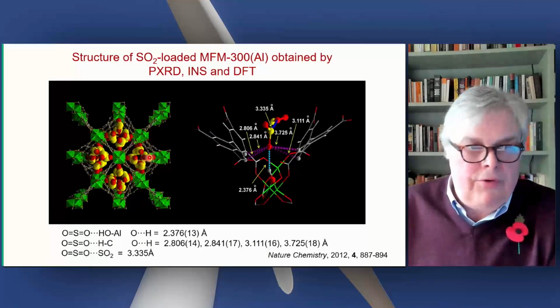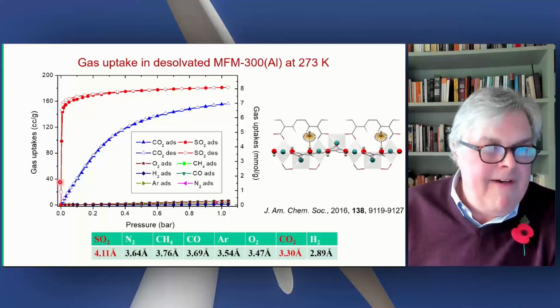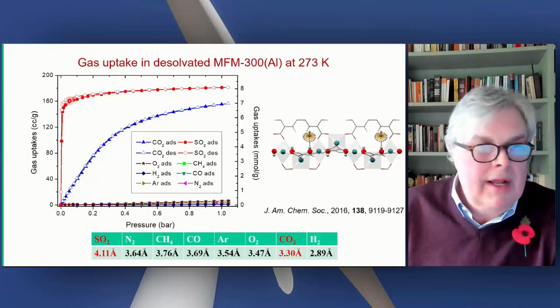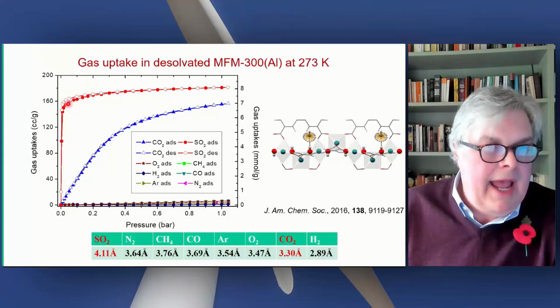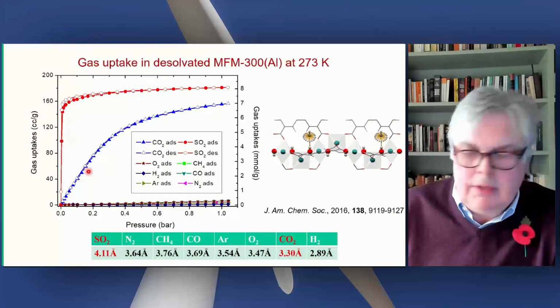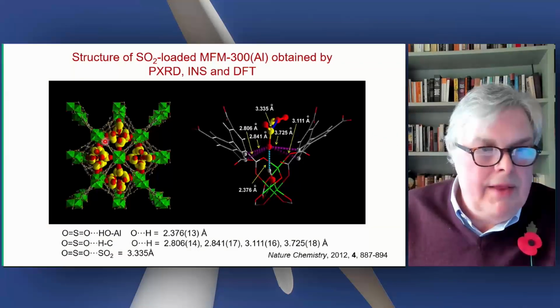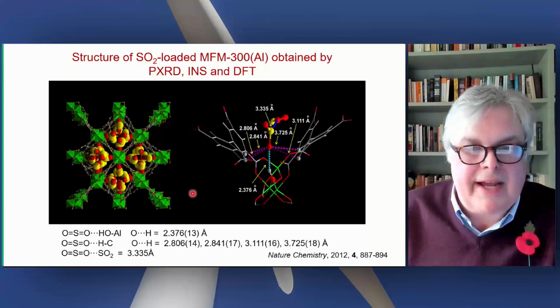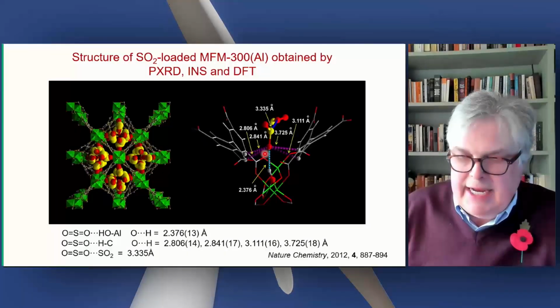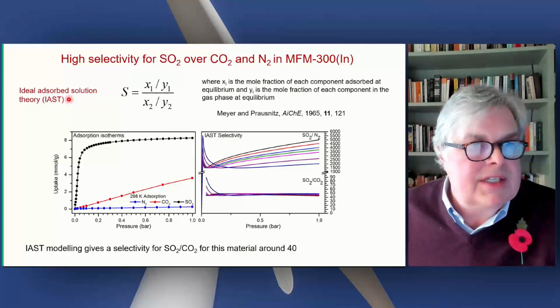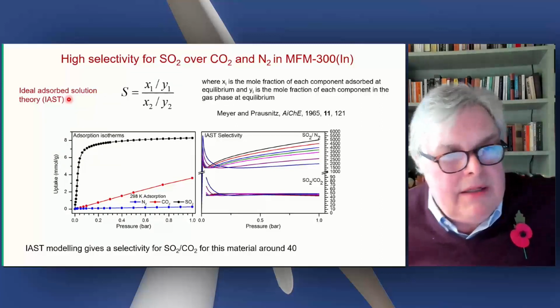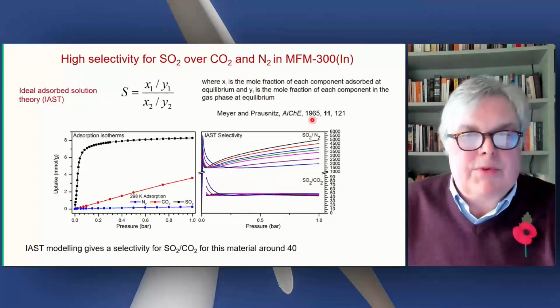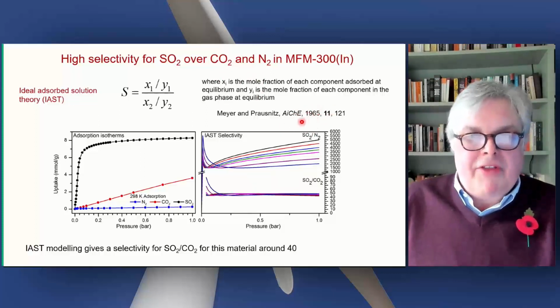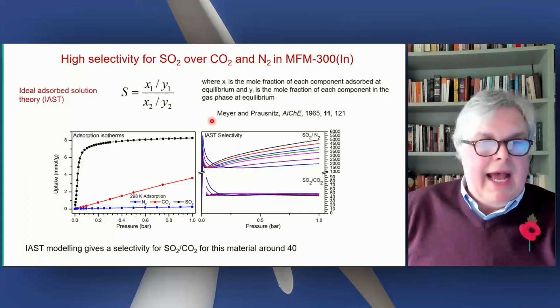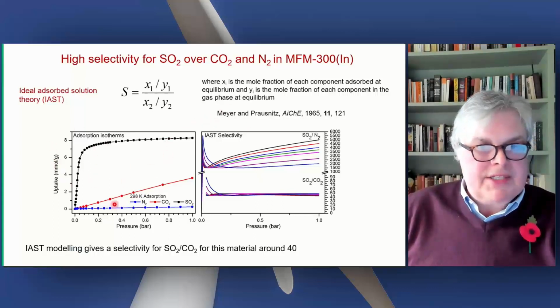And this, of course, if you recall, I'll show you again, a very steep uptake of SO2. That shows it has a very high binding energy at around 60 to 70 kilojoules per mole. And that's why at low pressures, this material takes up SO2 very effectively. And it is also very stable. We can use IAST theory, ideal adsorbed solution theory. This was reported originally in 1965, and the MOF community have really taken to this as a method of analyzing adsorption isotherms using this approach.